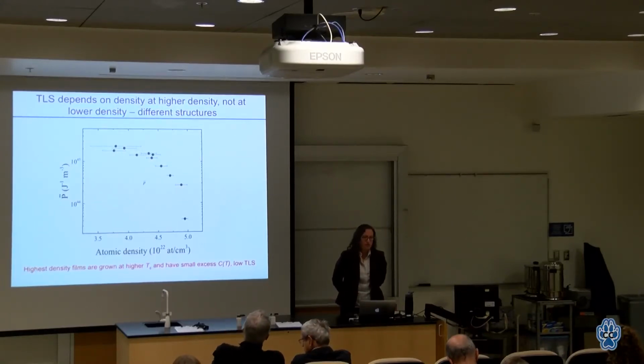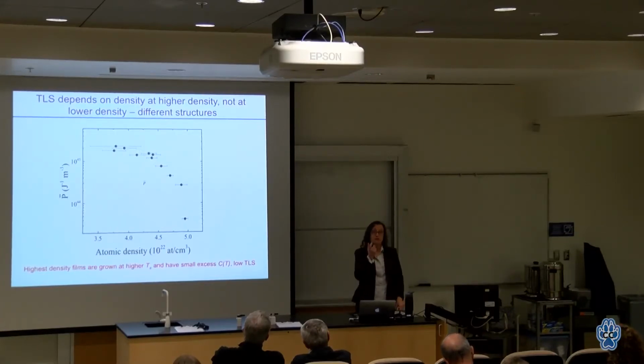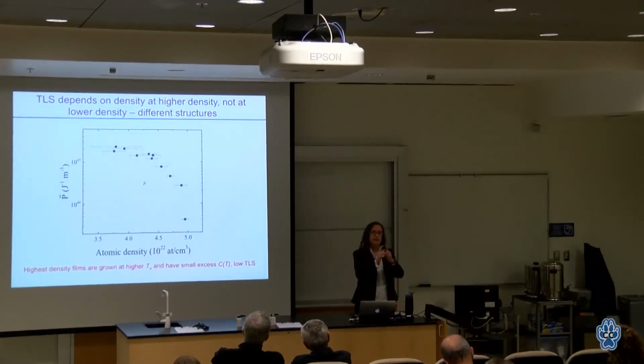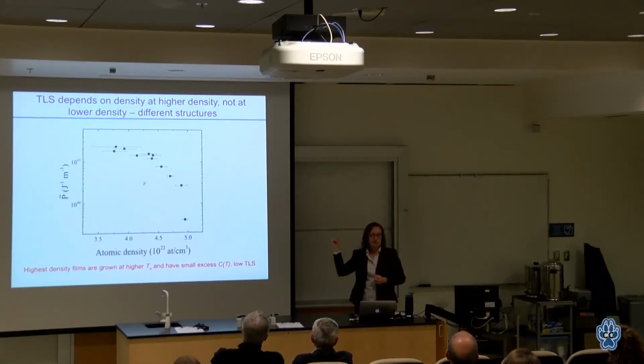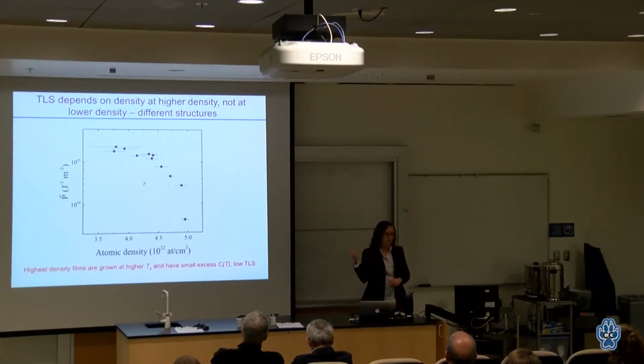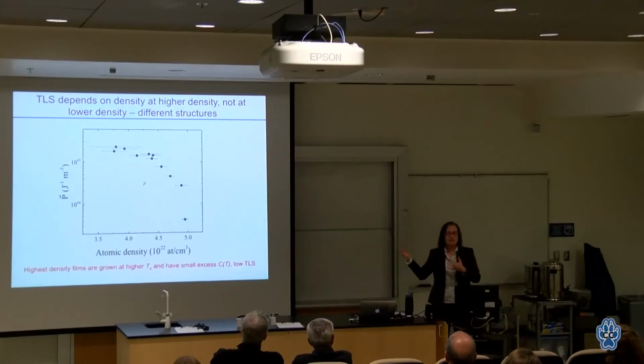One of the details in all of this is that perpendicular magnetic anisotropy, I think, is truly a local effect. It's really like individual terbium iron atoms. I think there's quite a good deal of local order that then gets lined up, as opposed to the silicon, where I think we're talking about slightly larger medium range order being what matters. So different effects will have different dependencies on thickness and rate and things like that.